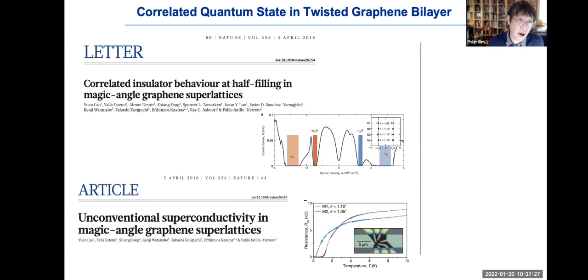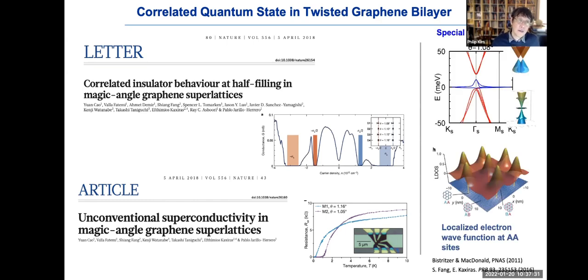In fact, this type of new phenomenon was what theory expected 10 years ago by considering the combination of van der Waals structures and Moire structures, with the small interactions across these van der Waals layers that can engineer a band, such as a flat band. And once this flat band appears in this magic angle graphene bilayer, a lot of exciting physical phenomena appear, such as superconductivity.